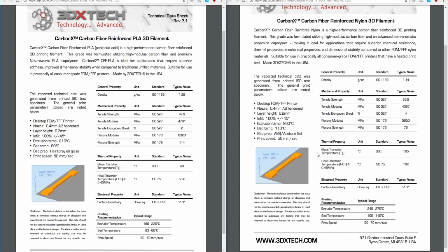So it would probably be neck and neck with carbon fiber PLA as far as the machine choices you would use it for. Nylon would be something you want to be tougher, stretch further before breaking, with almost better tensile strength, pretty close stiffness, so a pretty good load to deformation relationship. Flexural modulus is pretty close also, but flex is definitely not as good. If you're in tension, you're going to be just as good as PLA, and also stretch twice as far. But where it makes up the difference between that and PLA, number one, it's less dense, so it's lighter, and also the temperature stability, the dimensional stability under temperature, which is almost double.